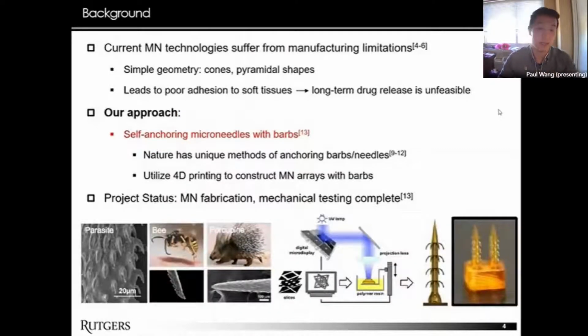So microneedles are not a new technology, but they do have issues which prevent their widespread use. As I mentioned before, current microneedle technologies are difficult to manufacture, which means that most microneedles are limited to simple geometries like cones and simple pyramidal shapes. And this is an issue because these shapes don't give great adhesion to tissue, so they can't stay in the skin long enough for long-term drug release.